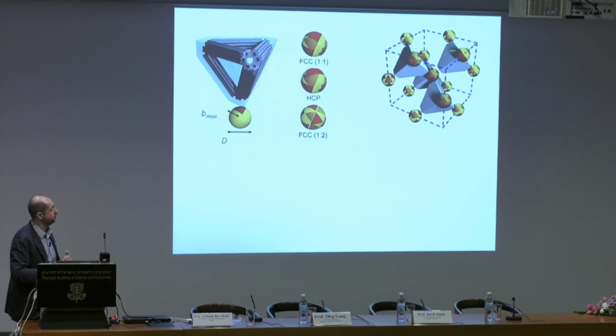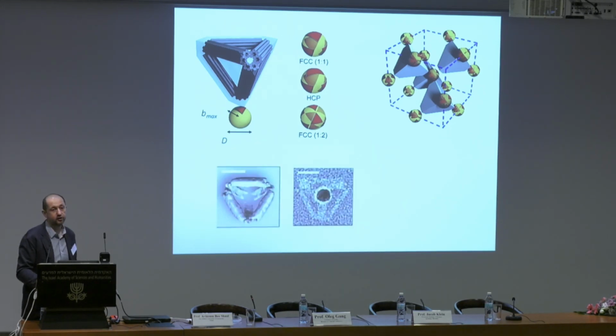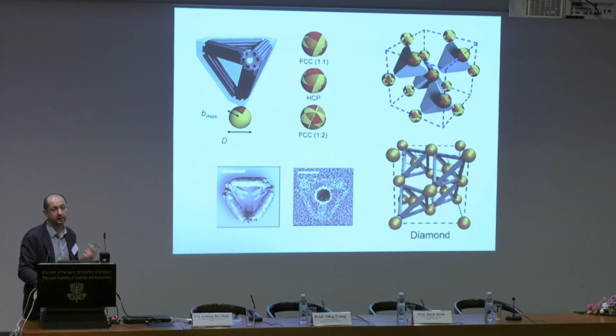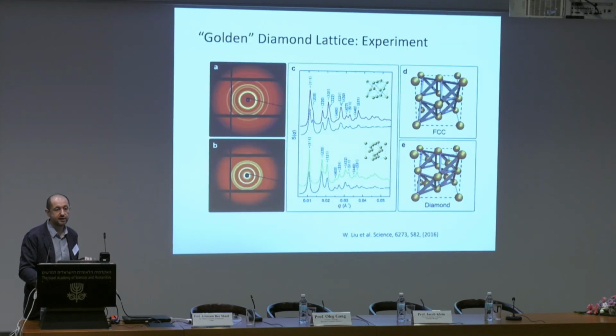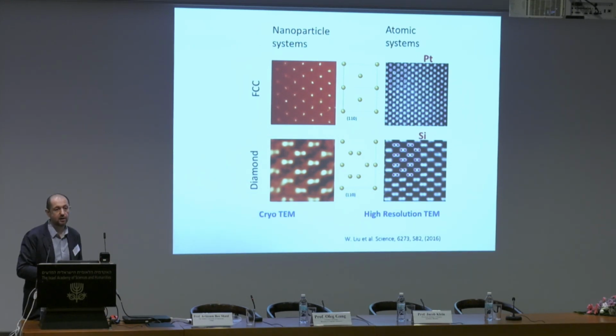Now, if you take this picture and project how it will look in 3D, it will look like that. And so from this point of view, you basically form an FCC lattice, which is a very simple lattice. Why go to such complexity to build such a complex lattice? The point is that this is an empty tetrahedral, and we can populate this tetrahedral with a particle inside, and that allows us essentially to build the diamond lattice from the point of view of particles. We can verify this using scattering, and we can confirm both FCC when there is no particle inside, and when we add a particle inside, we create diamond, as well as image using electron microscopy. This is the atomic system, FCC and diamond, and this is the system which we build, which is approximately 100 times larger.